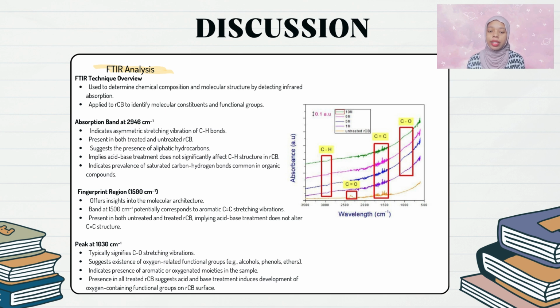Let's delve into the findings from the FTIR analysis. Fourier transform infrared spectroscopy, or FTIR, was employed to understand the chemical composition and molecular structure of the RCB before and after treatment. The FTIR spectra indicated several key features, the first being aliphatic hydrocarbons. We observe peaks corresponding to CH stretching vibration, which are characteristic of aliphatic hydrocarbons. These are typically found in carbon-based materials and suggest that the fundamental structure of RCB includes long-chain hydrocarbons.